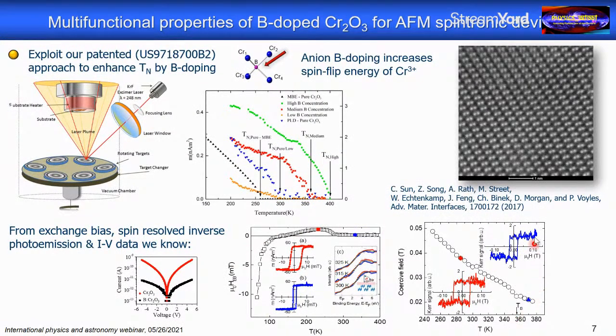So these were bad news for exchange bias systems. Somewhat good news was the fact that this material behaves dielectrically better. If you grow chromia films, chromia is a very good insulator. Actually, it's used in industry often as an insulating material. But if you grow it in thin films, you suffer from defects, which are prone to leakage. And the situation improved actually by boron doping. And you see that the leakage current is lower here in the boron doped material than it is in the pure material. That was good news.